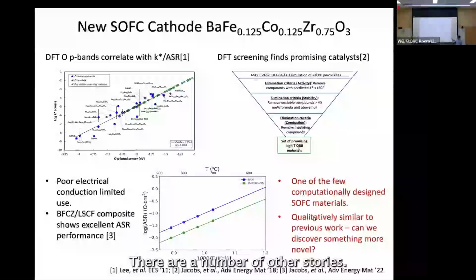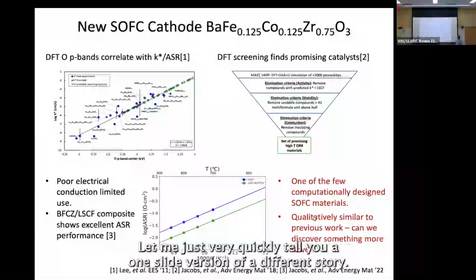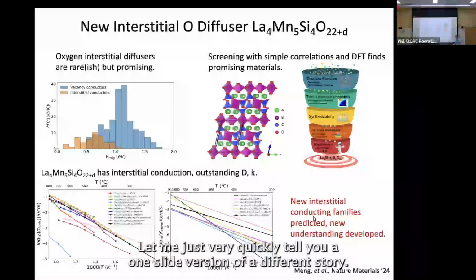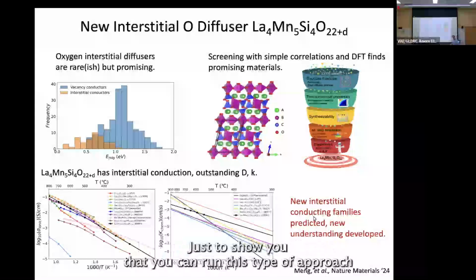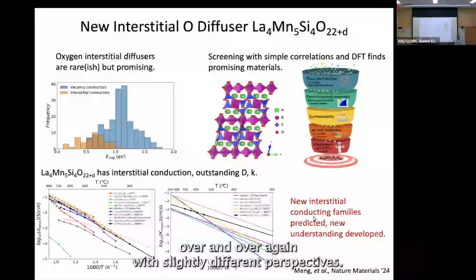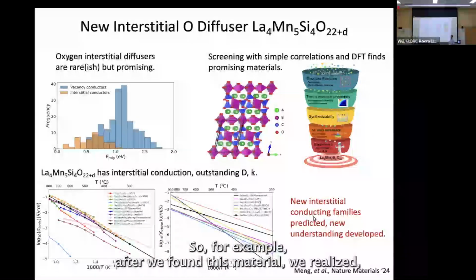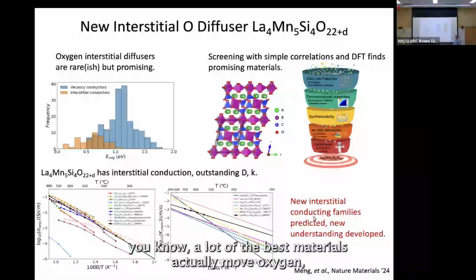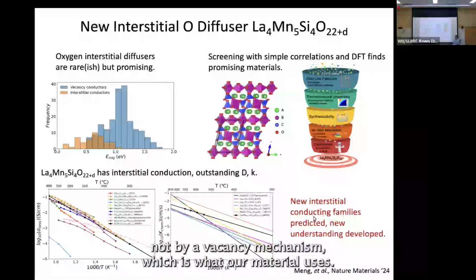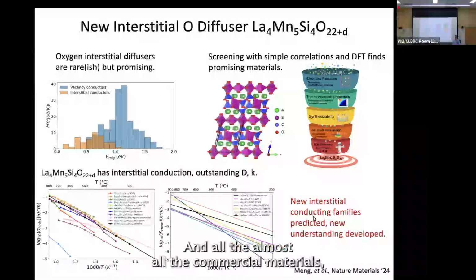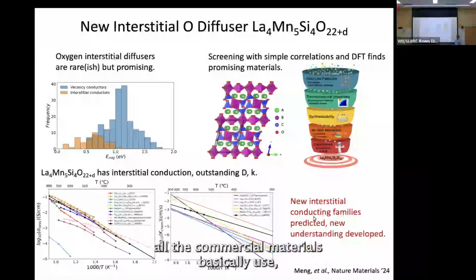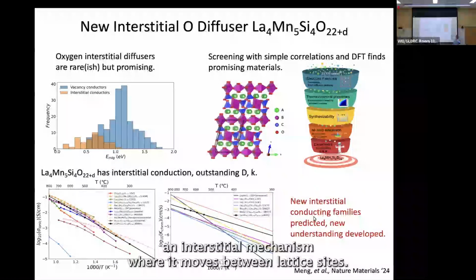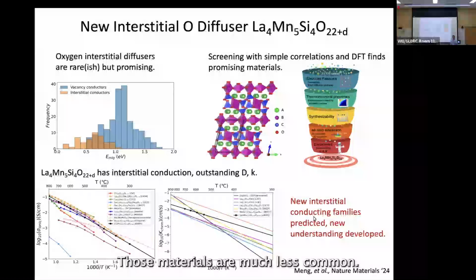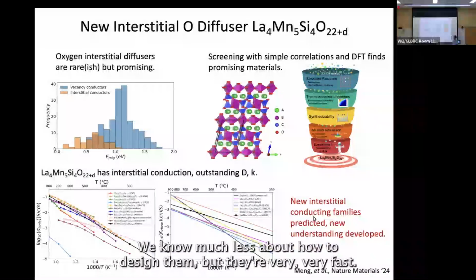There are a number of other stories. I summarized that story in a one-slide version. Let me very quickly tell you a one-slide version of a different story, just to show you that you can run this type of approach over and over again with slightly different perspectives. After we found this material, we realized a lot of the best materials actually move oxygen not by a vacancy mechanism, which is what our material uses, and basically all the commercial materials use. But oxygen can also be transported by what's called an interstitial mechanism, where it moves between lattice sites. Those materials are much less common. We know much less about how to design them, but they're very, very fast.